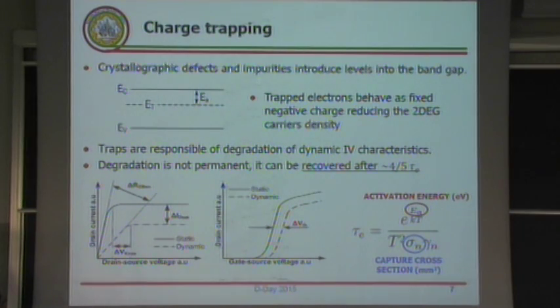And the problem is that because of trapping, we have a dynamic degradation of the performance of the device. So in a device with trapping, if we compare the static and the dynamic characteristics, we can observe a reduction of the saturation current, an increase of the knee voltage, an increase of the RDS on of the device, and a threshold voltage shift. These are unwanted effects because they degrade the performance of the device and they create instability.